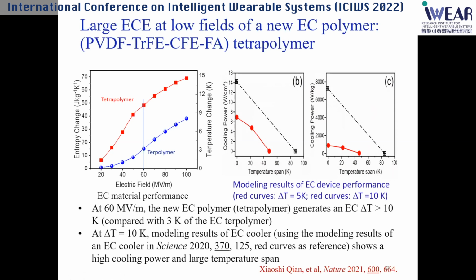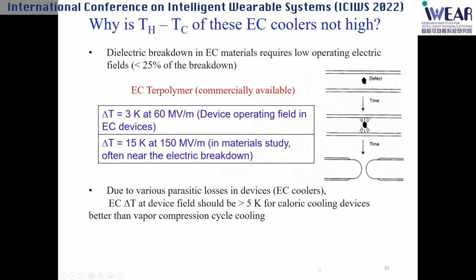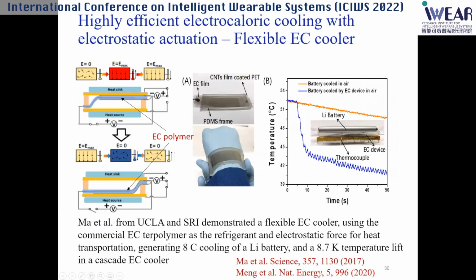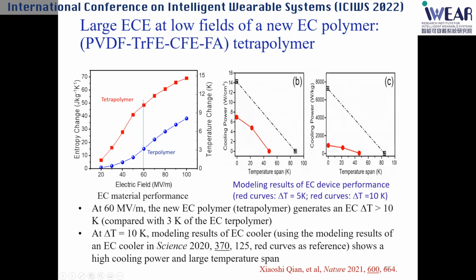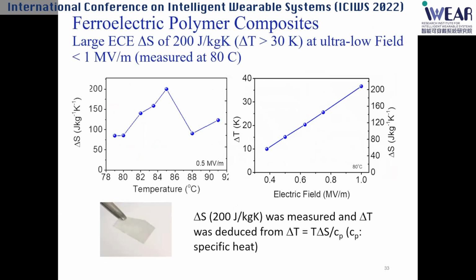Very high, about more than 5,000 watts per kilogram of EC material. This is the result we just published with colleagues in Nature last year. Also, by using a ferroelectric polymer composite, we find you can get this large EC effect at much lower electric field.